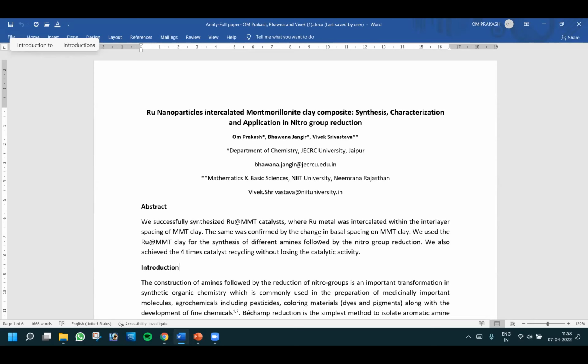As shown in my abstract, we successfully synthesized ruthenium MMT montmorillonite catalyst, where ruthenium metal was intercalated within the interlayer spacing of MMT clay. The same was confirmed by the change in basal spacing of MMT clay. We used the ruthenium MMT clay for synthesis of different amines by nitro group reduction. We also achieved 4-time catalyst recycling without loss in catalytic activity.